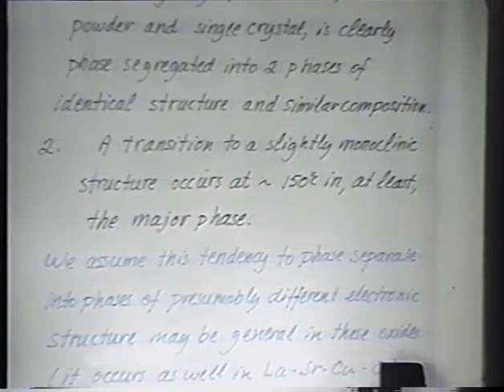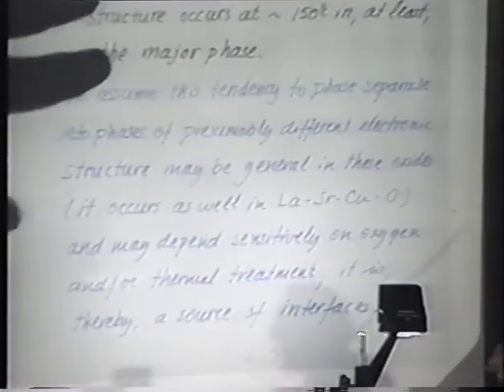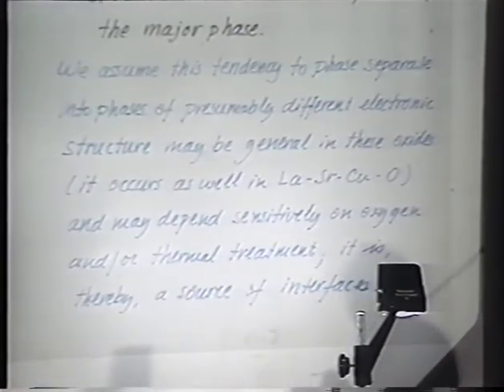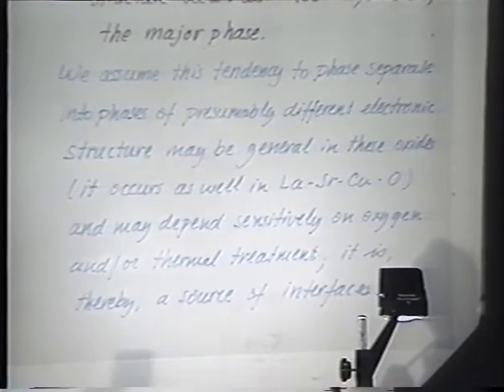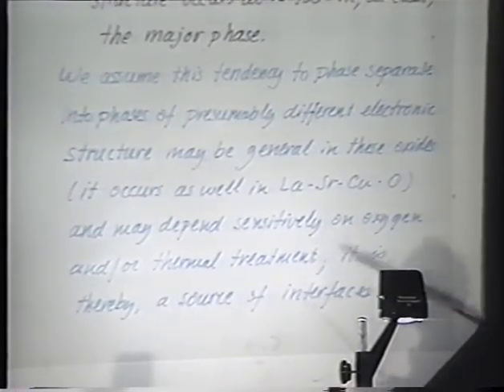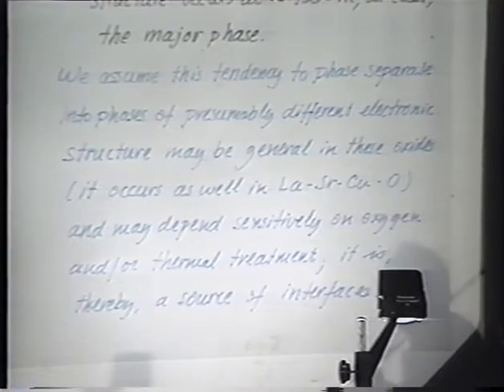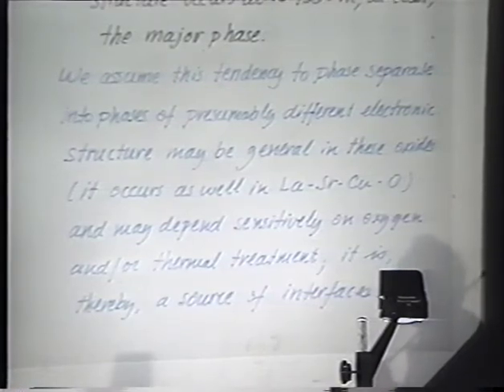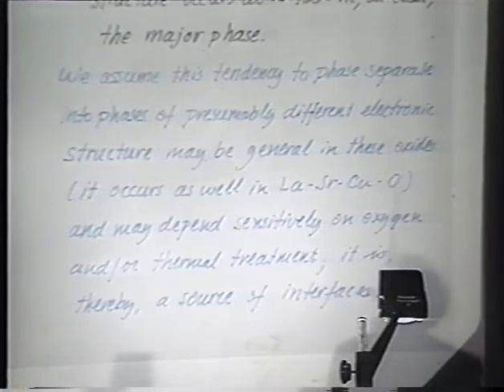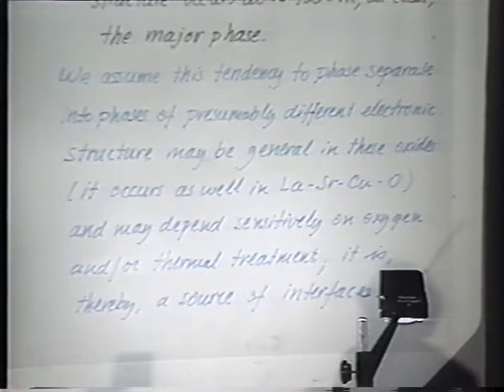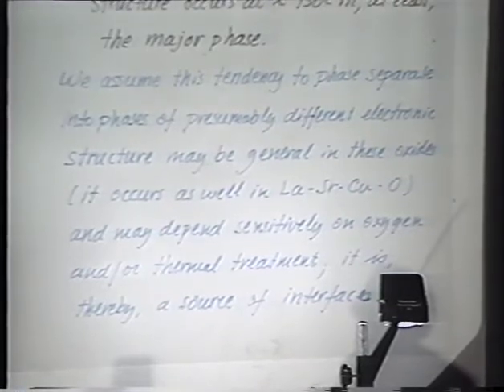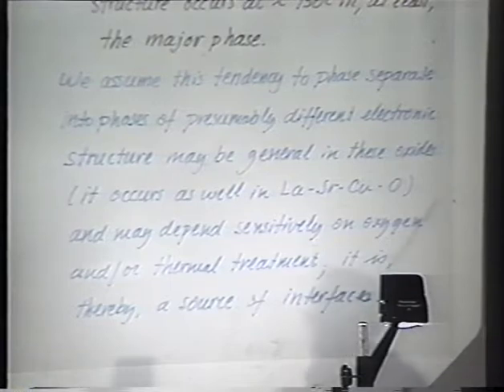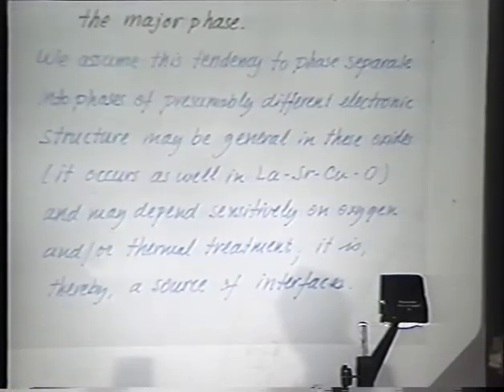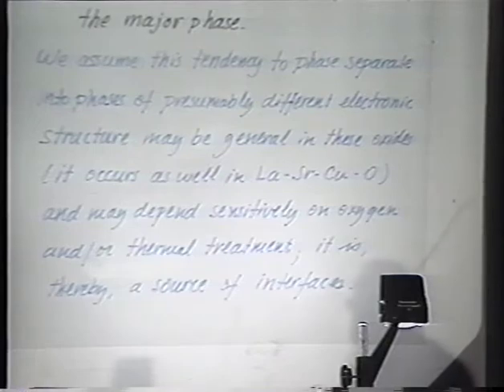In other words, it's either monoclinic or lower symmetry like triclinic. It's not orthorhombic. We assume the tendency to phase separate into phases of presumably different electronic structure may be general in these solids. We've also done measurements on the lanthanum, strontium, copper, oxygen system, and this may depend sensitively on oxygen and or thermal treatment. There's been a lot of talk this evening about the sensitivity of these materials to thermal treatment and to oxygen treatment, and we believe that the phase separation that we're talking about here is certainly one example of that. And if this phase separation exists, it's certainly a source of interfaces for those of you who like interfaces.